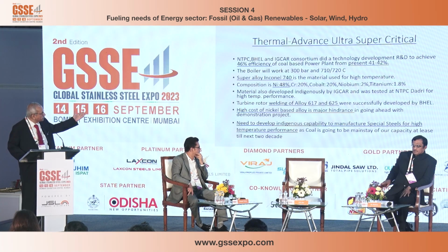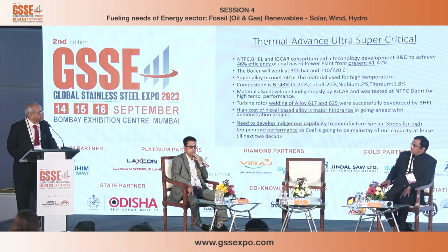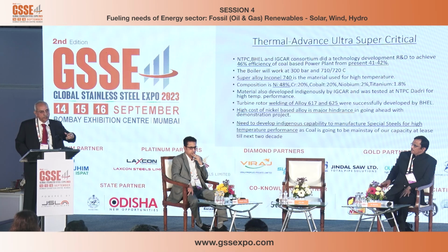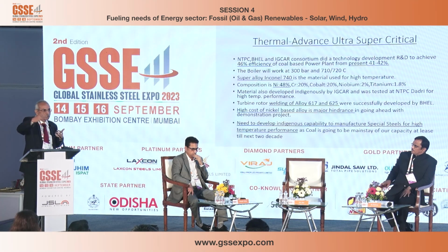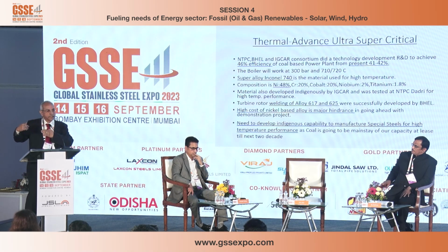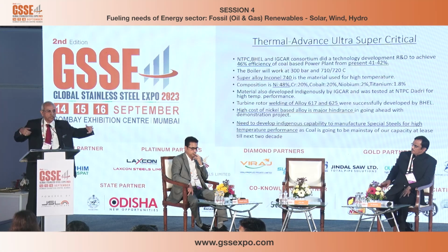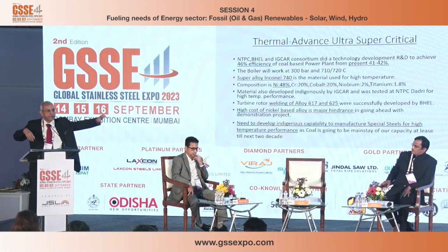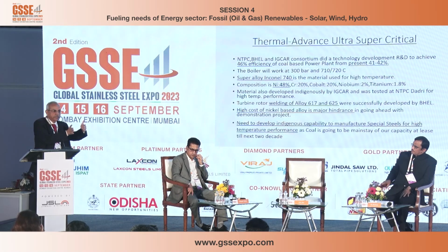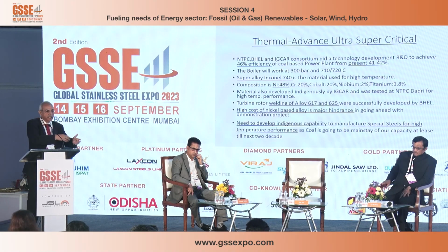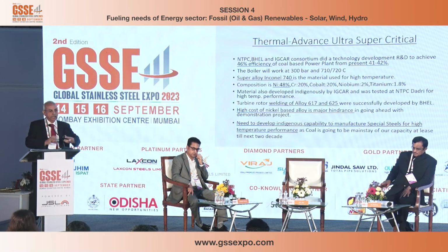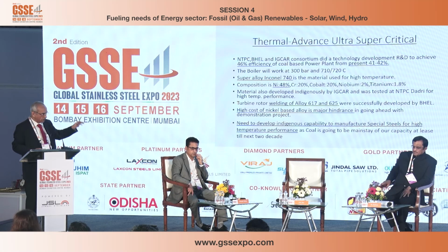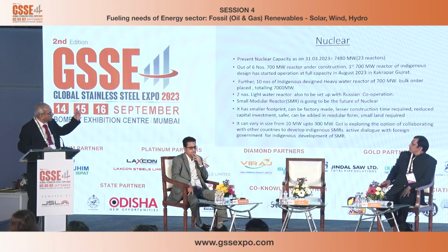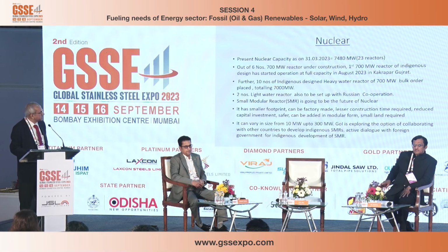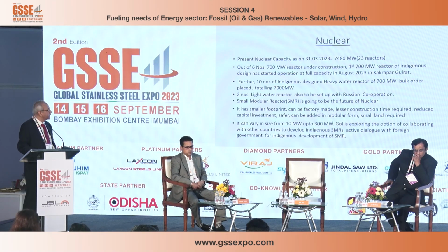We have also successfully demonstrated the welding of alloy 617 and 625 for the turbine rotor, because turbine, the first portion of the rotor will have a very high temperature steam coming at 710 degrees centigrade, and subsequent ones are the low temperature. So in order to reduce the cost, we don't want the entire rotor to be made of the high grade steel. So what we have done is, initial first stage we have given the high grade steel, and this other one is subsequently lower grade, and then we have tried to develop that welding technology, which was also successfully demonstrated.